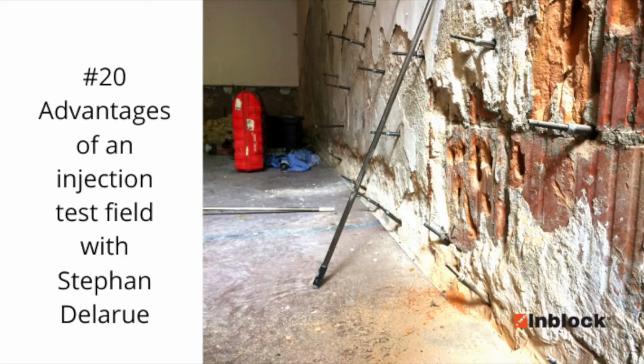And a lower foaming factor will reduce it, but you will also get 30 or 40 Newton per square millimeter. So the target was to find out the spreading of the material inside the structure, the packer distances, the amount of the material, which can be calculated after the test injection zone. And at the end, we also did some core drillings at some spots to really check the structure and the strength of the concrete we achieved with that test injection.